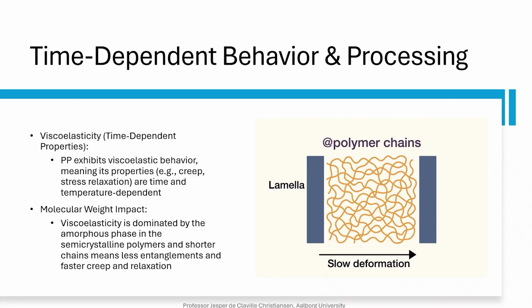There are other types of load, like creep. And in creep, we have time dependency. And here suddenly the deformation is not in the lamella, in the crystalline regions, but it is between the lamellas, in the polymer chains. And this is where it gets important that we have a scission of chains, that they get shorter, and the time scales get shorter as well, because now suddenly the chains are more free to move around.